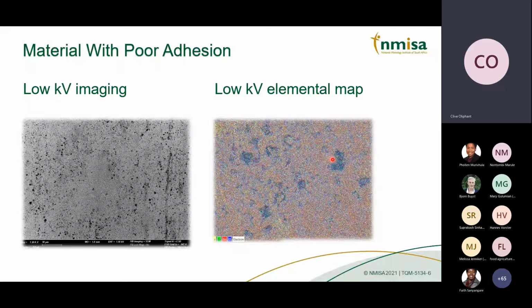This is another example of how advanced measurement solutions are required for these advanced materials. Viewing this material using normal SEM parameters, it's not so easy to distinguish these dark regions. However, dropping the voltage down very low, now we can start to see these black spots.